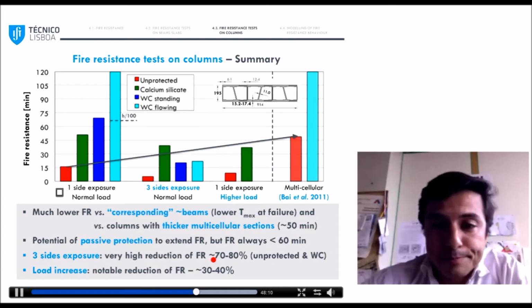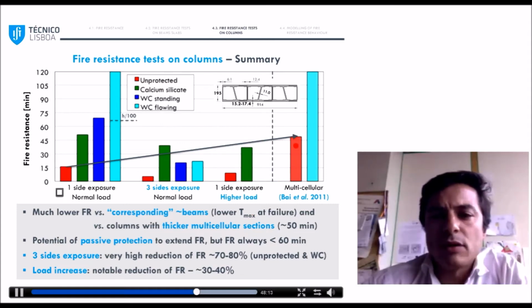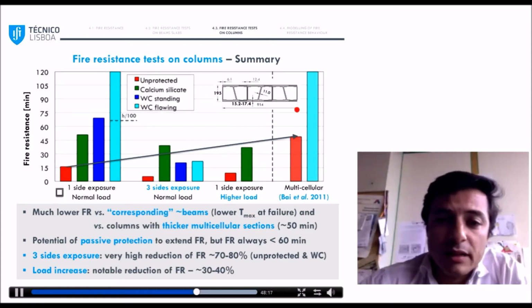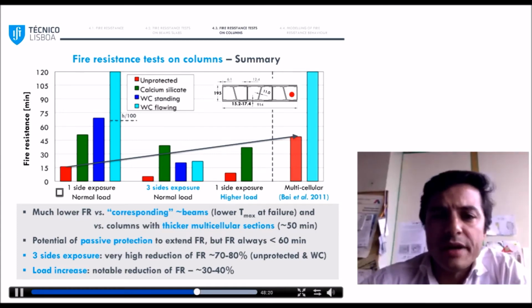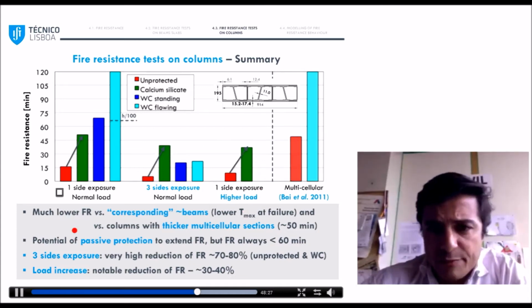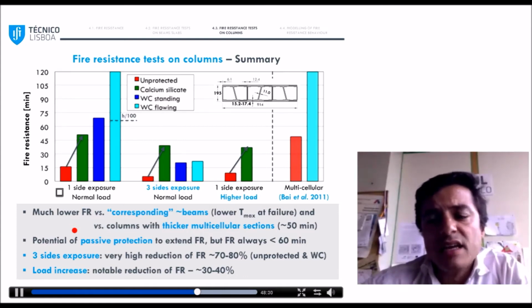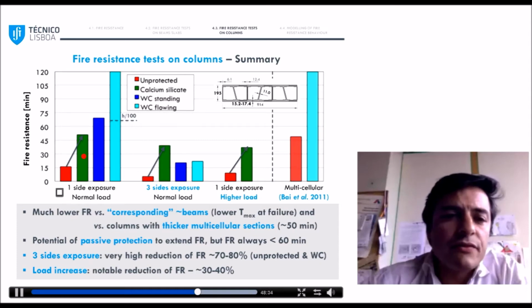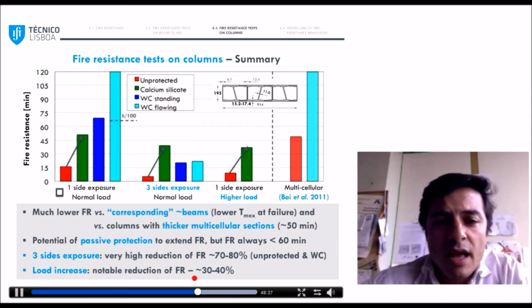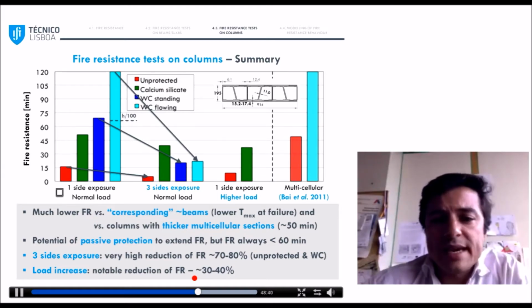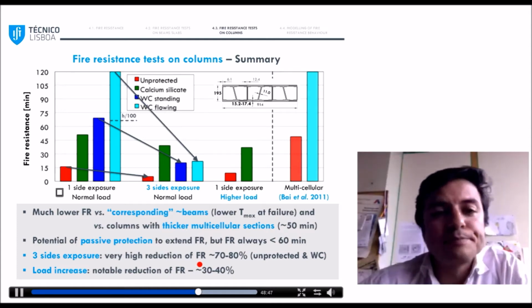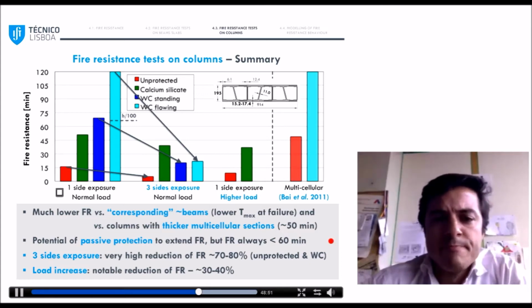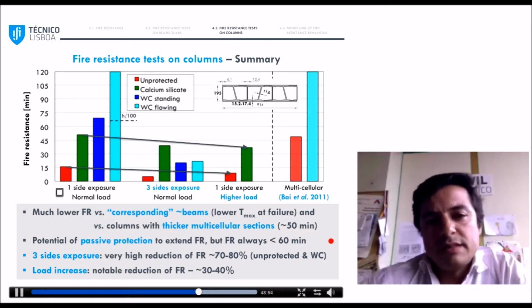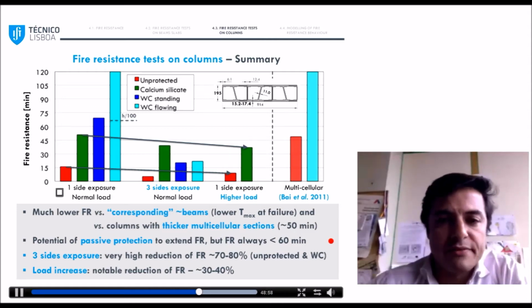Again, lower than the resistance of the multicellular panels that were tested at EPFL, as I mentioned, with higher height and wall thickness, that reached about 50 minutes of fire resistance. So passive protection, in spite of its efficacy, we could not get to the 60 minutes, even for one side exposure. And you can see that for three side exposure, the performance was again drastically reduced, especially for water cooling, either standing or flowing. And as for the beams, and as expected, load level also influenced the fire resistance of the columns.